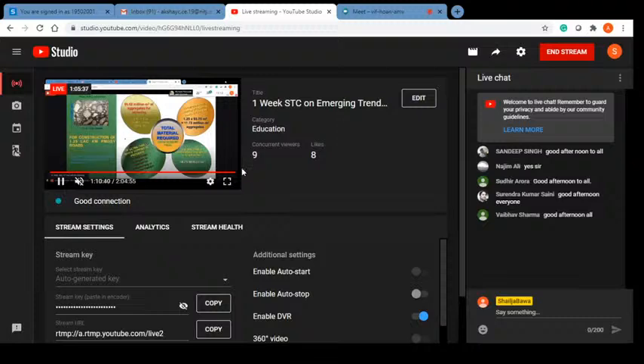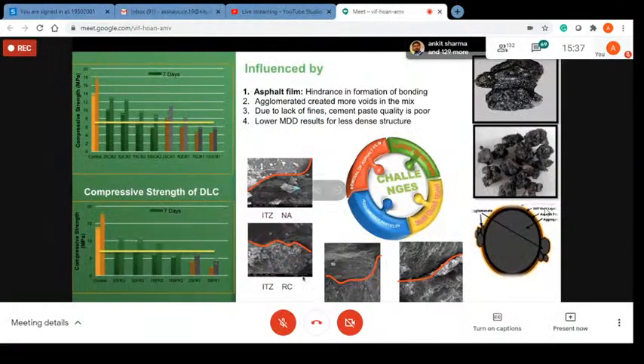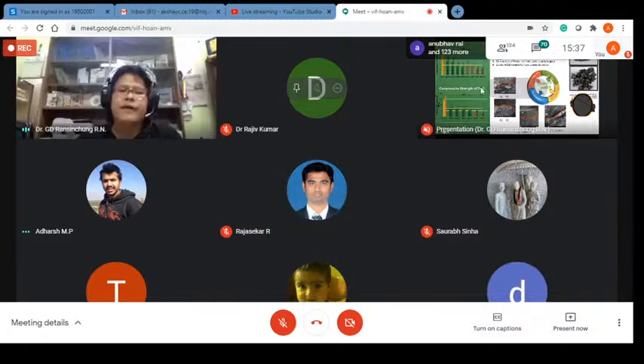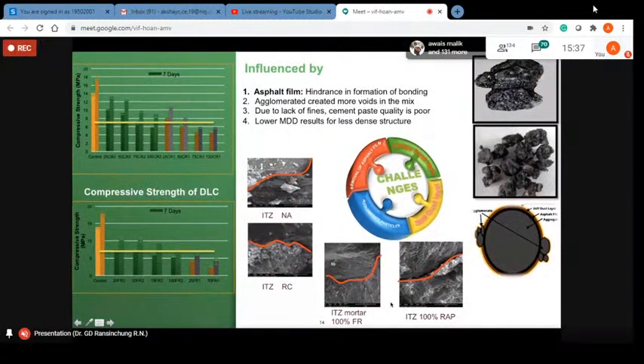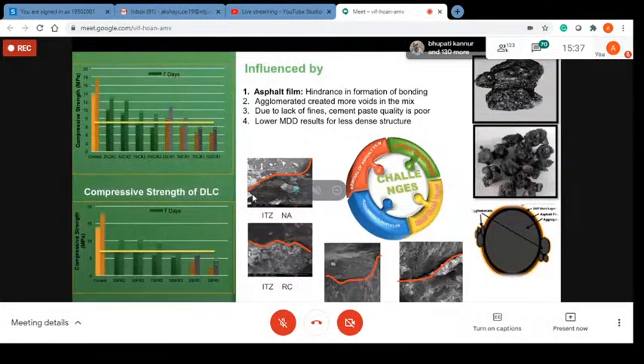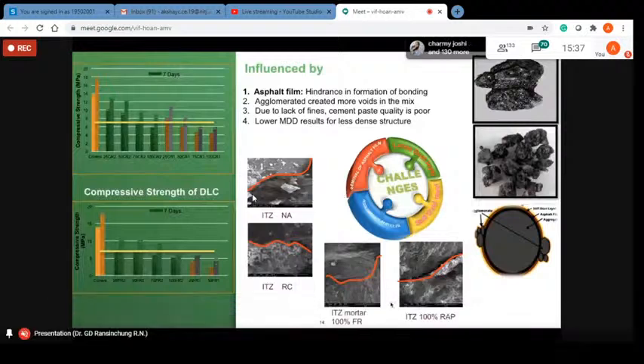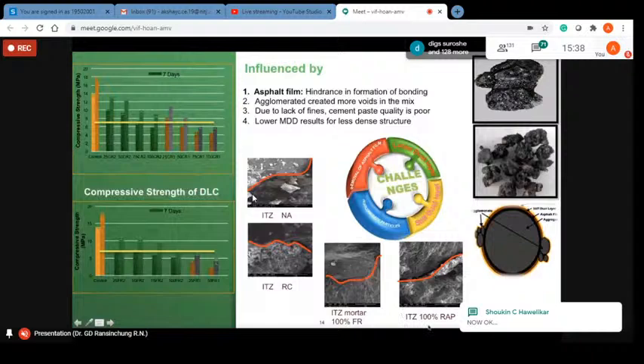Now, in order to understand better, we tried to capture images. These images were taken from the mortar study only, not for the coarse aggregate, coarse RAP materials. This is by including the fine RAP, and we tried to understand the mortar performance, what exactly is happening in the interfacial transition zone between the aggregate particles and the hydrated paste. Here, NA represents natural aggregate, RC represents the coarse RAP materials, and this ITZ mortar is for 100% fine RAP, and ITZ for 100% RAP.